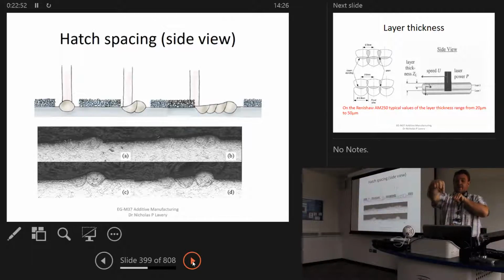And the next time the laser comes back, you've got a level of overlap. So that hatch spacing has been done to create a bit of overlap. But because of the melting, the fact that you're remelting, you get a bit of a slump. So if you keep on doing that repeatedly, what you find is that you get a bit of a slump in the solidified material, which again has to be compensated for when the powder comes back the next time, which is why none of this is absolutely precise down to that level. And that's the one thing to be really clear. Just because you set something in the machine at 50 microns, you don't have a nice 50 micron layer, you have a 50 micron layer with lots of undulations and imperfections.